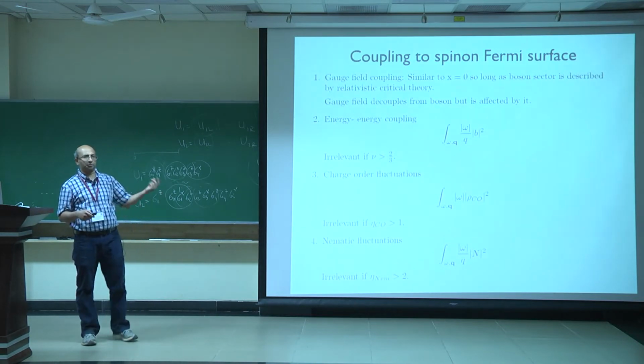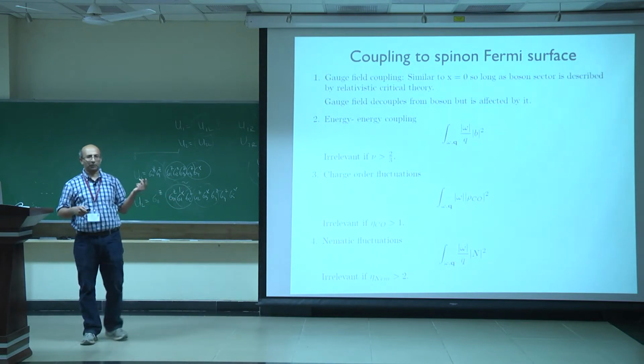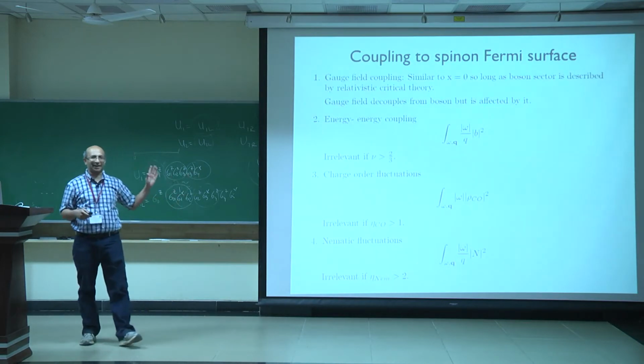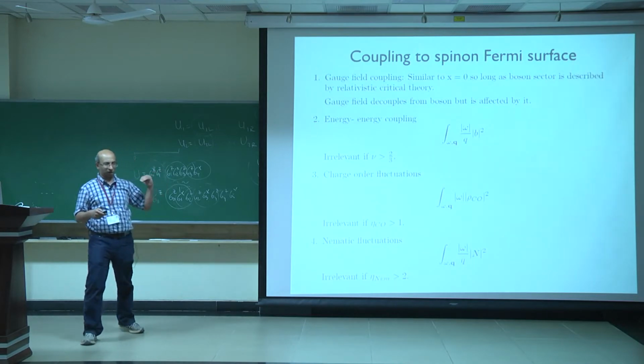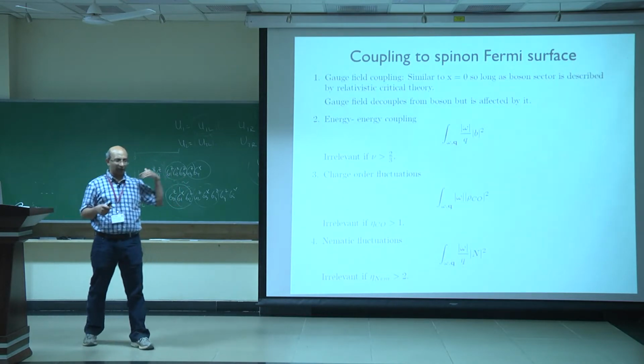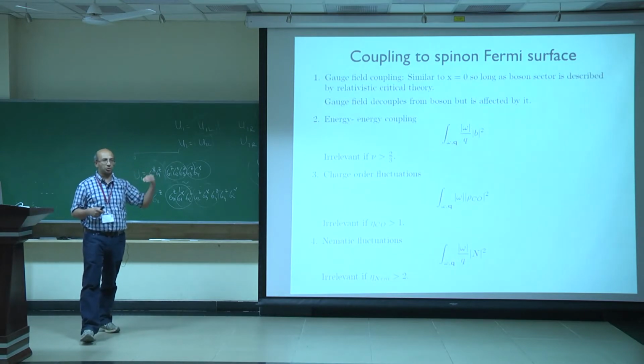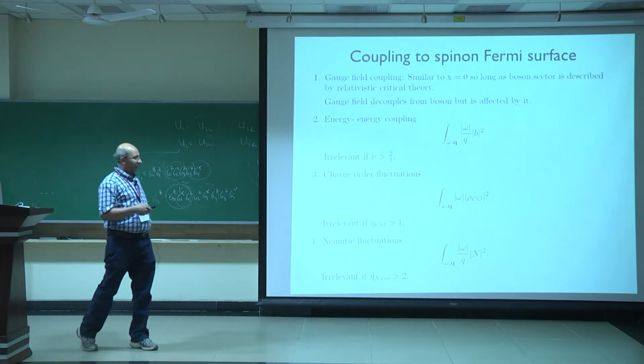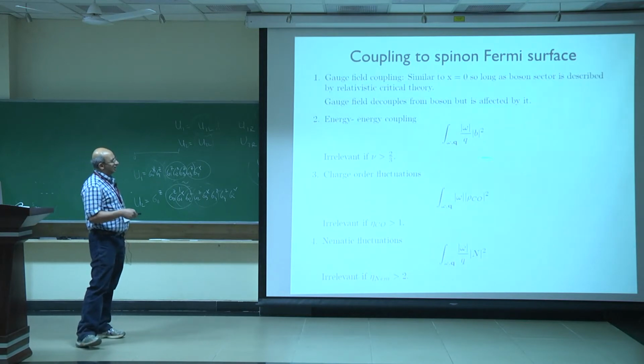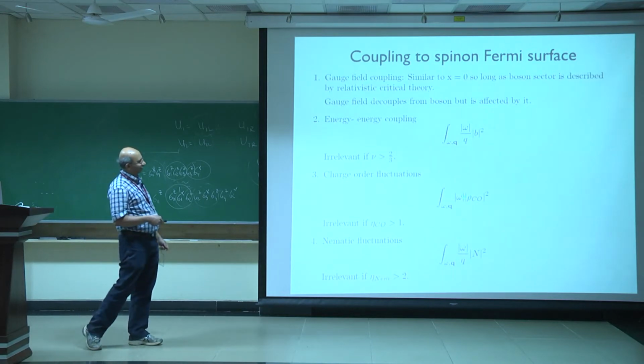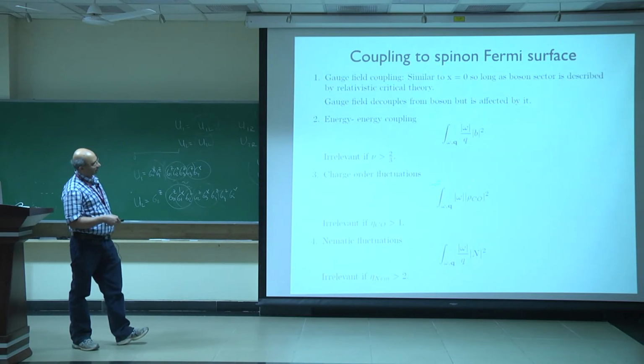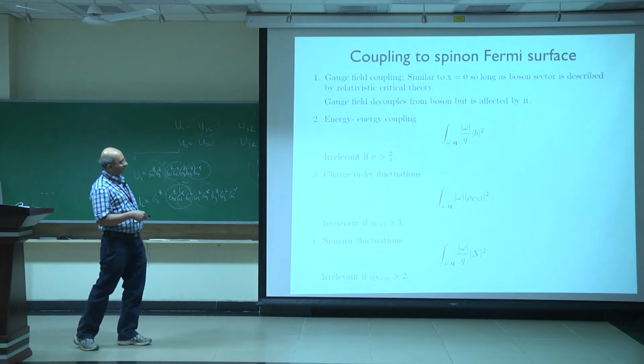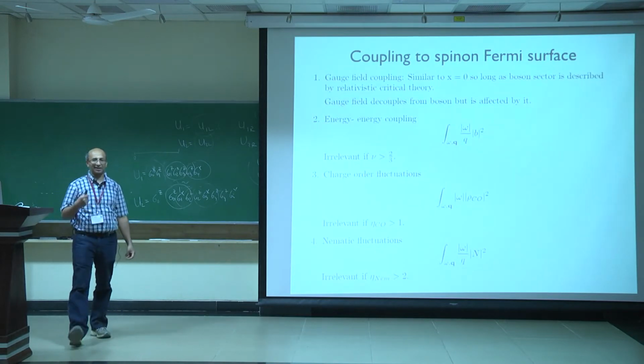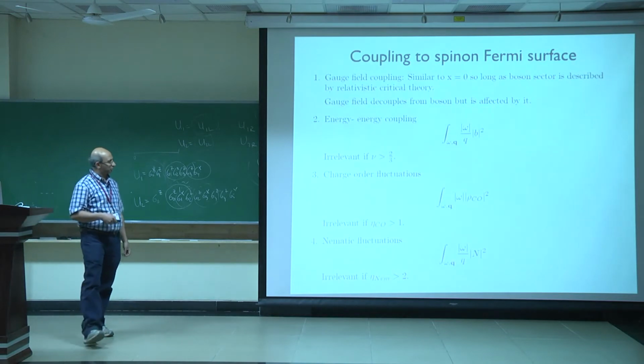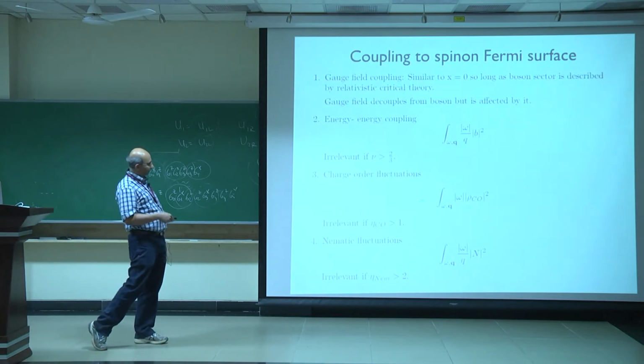It's a term that couples to a bilinear of the fermions. Okay? And in fact, it's a standard coupling that's kept in theories of conventional phase transitions, the so-called Hertz-type theories associated with the onset of charge order in a Fermi liquid metal. Okay? Now, that coupling will lead, so the fermions will then lead to a Landau damping of these charge order fluctuations, which takes this form. And you can ask when this is irrelevant at the bosonic fixed point, and it turns out that it's irrelevant if eta charge order is bigger than 1.